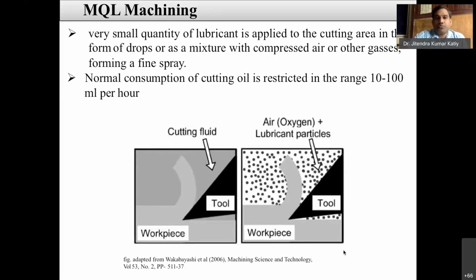So we now move to minimum quantity lubrication machining. Here, as I told you, we are using a very small quantity of lubricant, and that is applied on the cutting zone. This minimum quantity lubrication is applied along with compressed air. In that particular lubricant, you can add nanoparticles. Those nanoparticles can impinge on the cutting tool with the air. Normal consumption is restricted to 10 to 100 ml per hour according to the flow rate we have given.